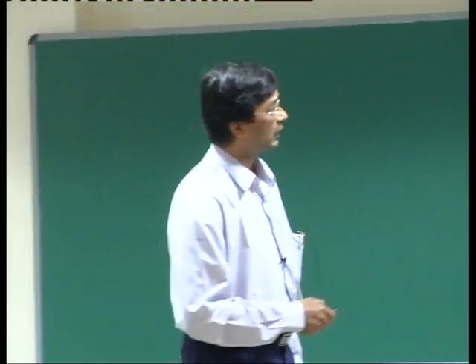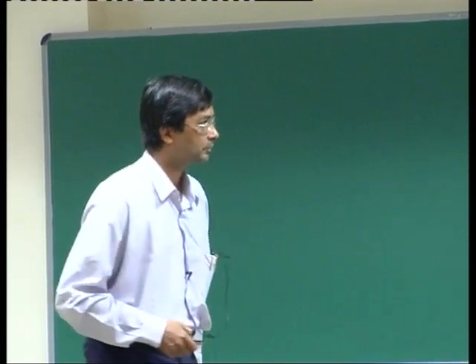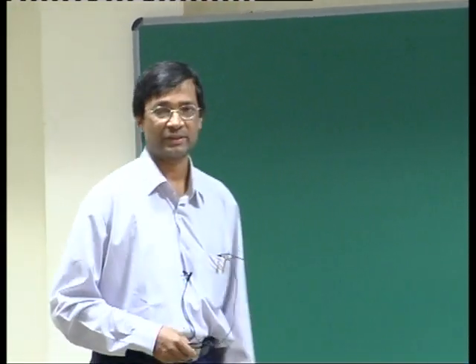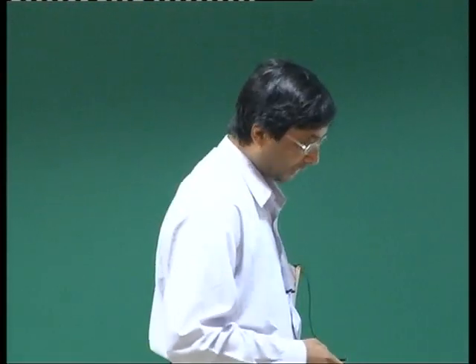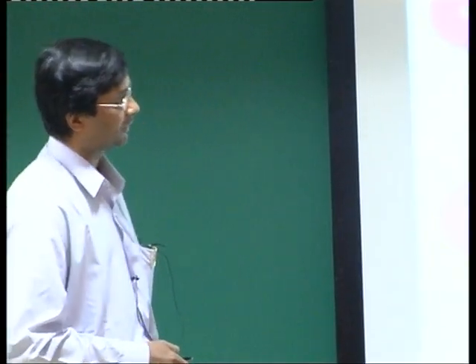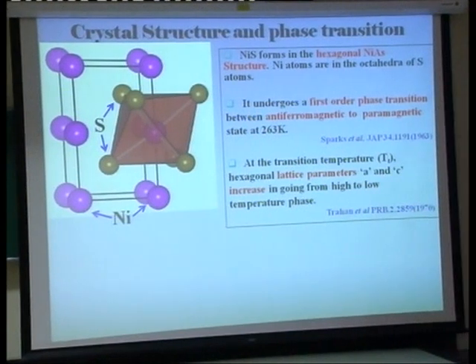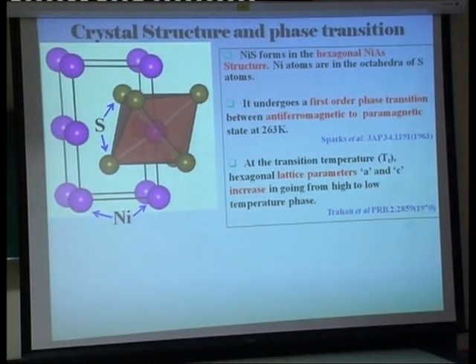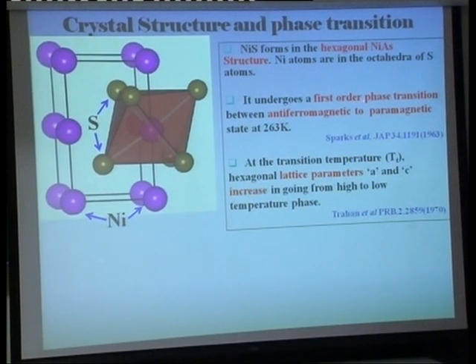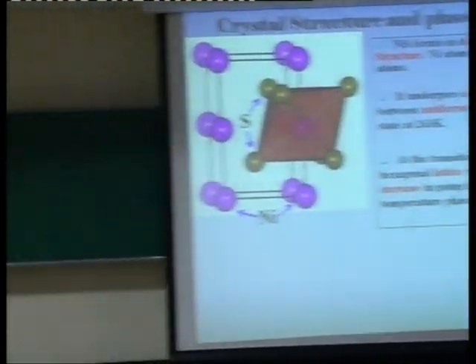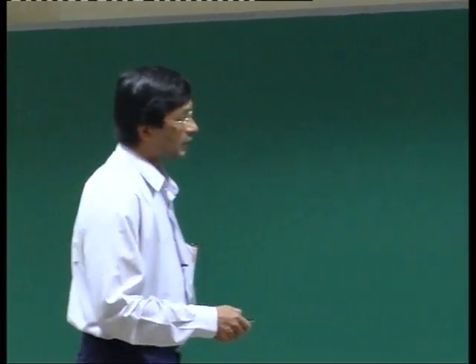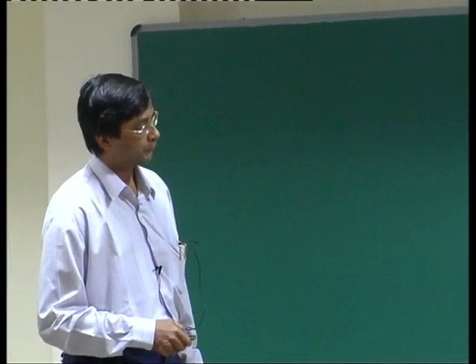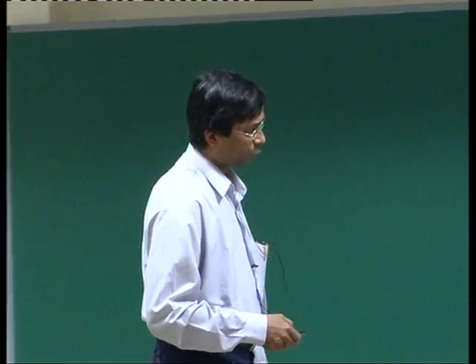But I've also mentioned the phase transition. It turns out that it has a very spectacular phase transition. The structure type is known as the nickel arsenide structure type. This first order phase transition is at about 263 Kelvin. It is more or less understood and agreed upon by everybody that the high temperature phase is a paramagnetic state and the low temperature state is an antiferromagnetic state. So there is, experimentally at least, not a very large amount of disagreement about the magnetic structure, though we do believe that there may be some twists and turns even in the magnetic structure at low temperature, but that will not be the subject matter of today's talk. So it is a very strong first order transition at 263 Kelvin. And there's a small change in the volume, which changes by about 2% across the transition. The volume is larger at the low temperature.